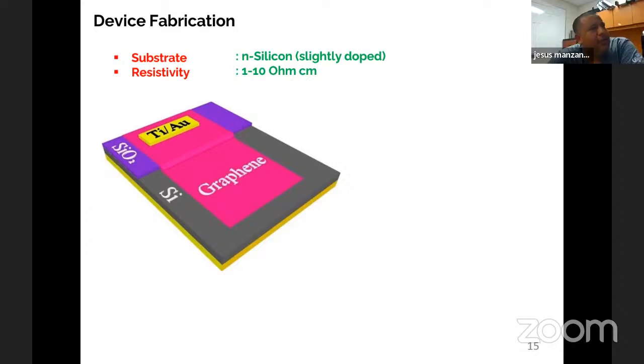Dharma, how thick is this graphene layer? Is it monolayer or bilayer? This is monolayer. Sometimes I even use bilayer also, but not more than bilayer. Experimentally, you do monolayer graphene? Yeah, experimentally I do. I did fabricate monolayer graphene by CVD.